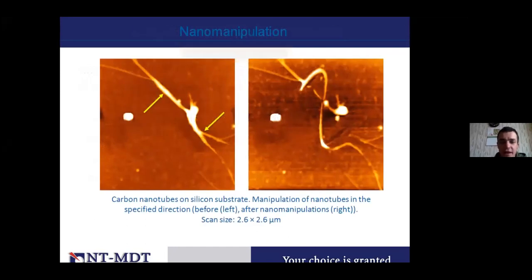And here is a slide which represents one example of how we can use the AFM to modify the surface. For example, here you can see the image of the carbon nanotubes on the silicon substrate. The size is below 3 microns, and on the left you can see the image of the carbon nanotubes obtained without any deformation or strong interaction between tip and the surface. And then we use the tip as a nanomanipulator, and we move it left to right, and we turn the nanotube on the surface by applying a bit higher force.